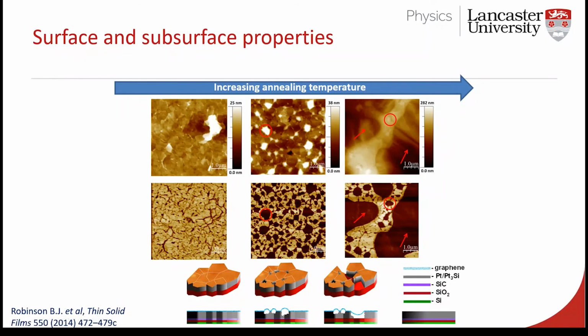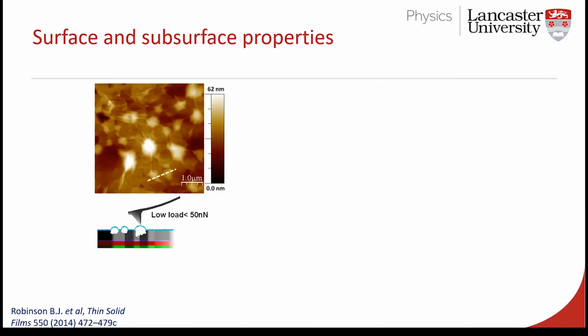This is information you wouldn't access normally just by looking at the surface, certainly not from an SEM or a technique like that. So we were able to go back to our collaborator and say, you have bubbles, you have domes forming. So you need to adjust your catalytic substrate, and you need to adjust your annealing temperature. We started to be able to feed back directly into their manufacturing process now to help them solve these problems.